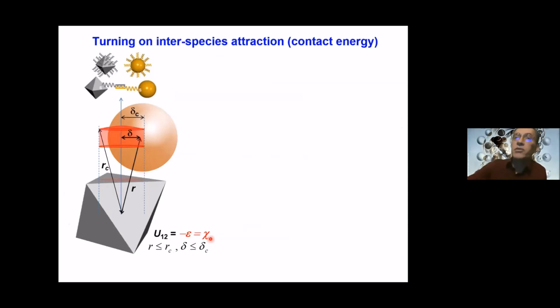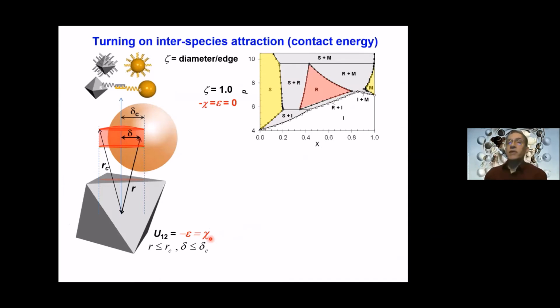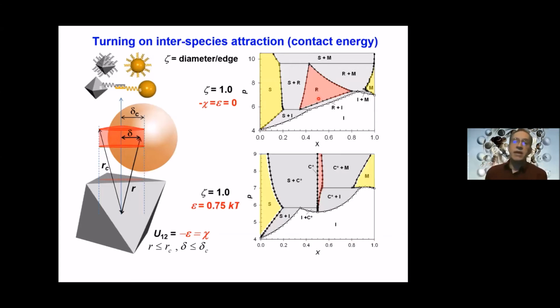So first, let me show you the phase diagram that you will find for a size ratio of 1 and epsilon 0. So it's athermal. So similar to what I showed you before, we found this R phase right in the middle. Now I'm going to change epsilon to be 0.75 kT. So you see that there is a significant change in the phase diagram.